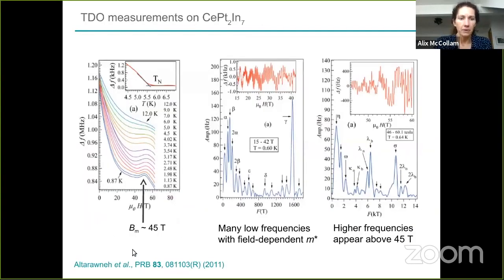Okay, so these are the measurements I was talking about. These were done in Tallahassee. These are tunnel diode measurements of cerium, platinum, 2, indium 7. So these are transport measurements, basically. It's a metallic system, and the tunnel diode is measuring at a relatively high frequency, but effectively it's probing the skin depth of the material, which is related to the resistivity. So from the change in the tunnel diode resonance frequency as a function of magnetic field or temperature, you can extract information about the resistivity.